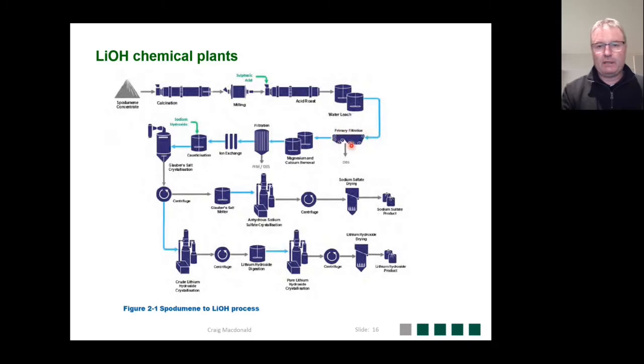We then pass the slurry into a liquid solid separation step, and the lithium is in the liquor. Magnesium and calcium are precipitated out. We then clarify the liquor in a filtration step. The lithium is then concentrated in an ion exchange step. Sodium hydroxide is then added and it is passed onto a Glauber salt crystallizer. Glauber salt is actually hydrous sodium sulfate. The crystals from the Glauber salt crystallizer go to a liquid solid separation step in the form of a centrifuge. The solids from the centrifuge are then remelted and recrystallized in an anhydrous sodium sulfate crystallizer, passed on to another centrifuge, dried, and then the sodium sulfate is bagged and sold off as a byproduct.